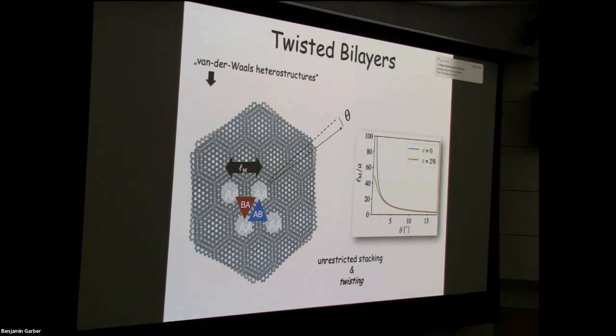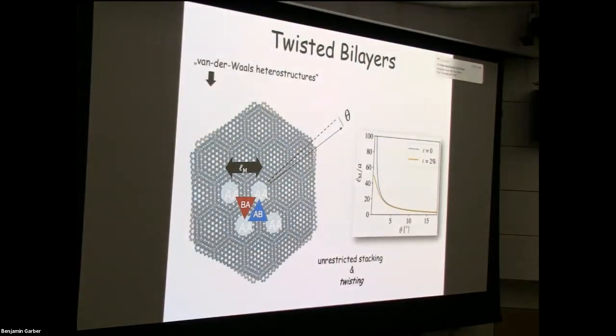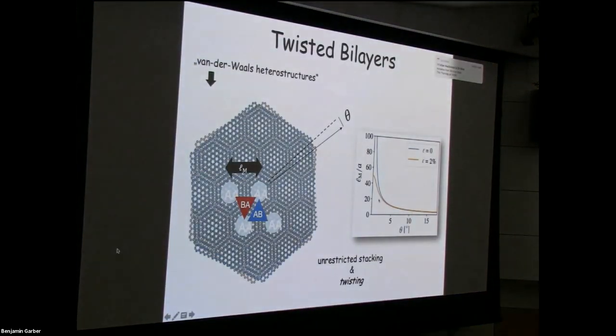The smaller the twist angle, or this plot here allows for a difference in lattice constant, the strain, if you like. The smaller the twist angle, if there's no difference in lattice constant, the Moiré period just goes like one over the twist angle, and you can, in principle, get any lattice constant for this periodic pattern from zero to infinity.